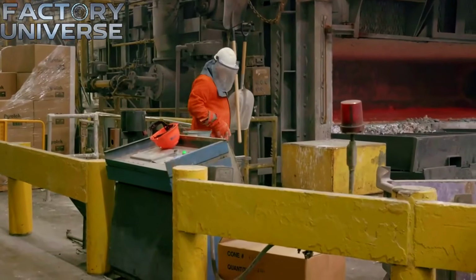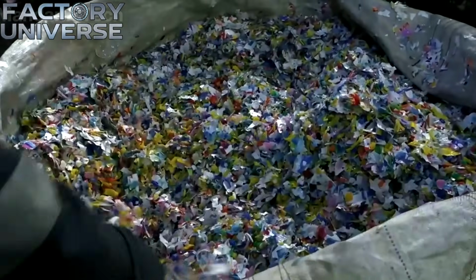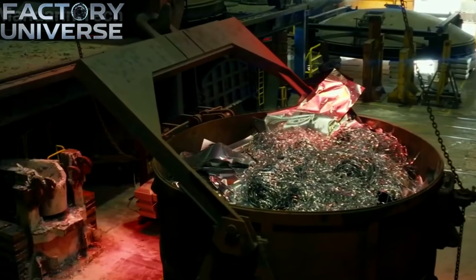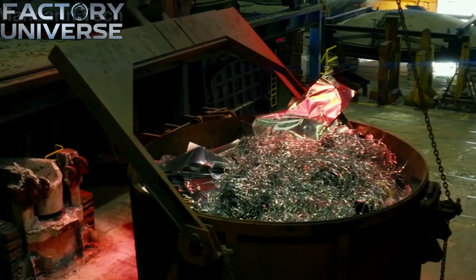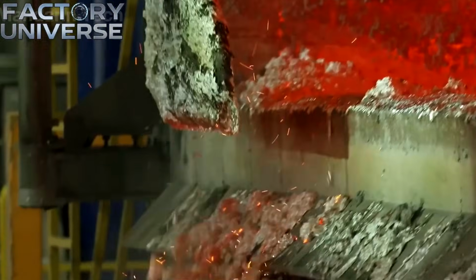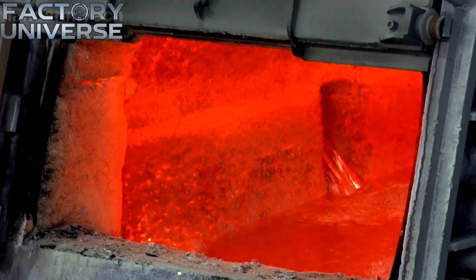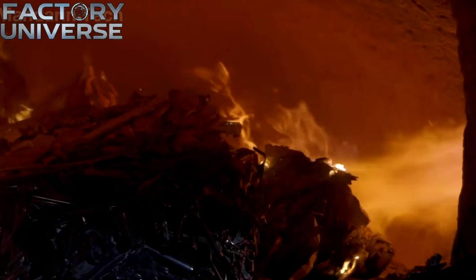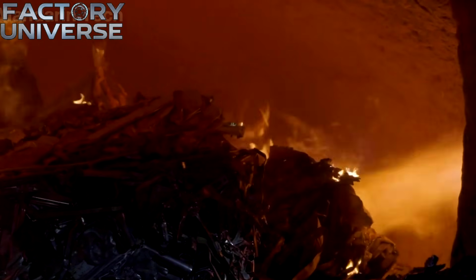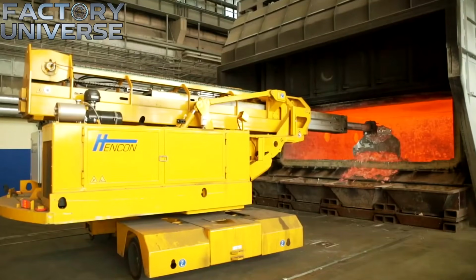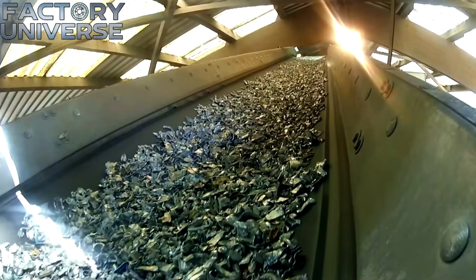Slag floats up like silvery foam to the surface of the liquid metal. This layer is then skimmed away either mechanically or by hand to leave behind a purified material. In more advanced setups, inert gases like argon or chlorine are injected at low pressure. Tiny bubbles pass through the molten aluminum, capturing excess oxygen and hydrogen and lifting them to the surface for removal. Everything only gets more complicated as the metal reaches its final purity level.